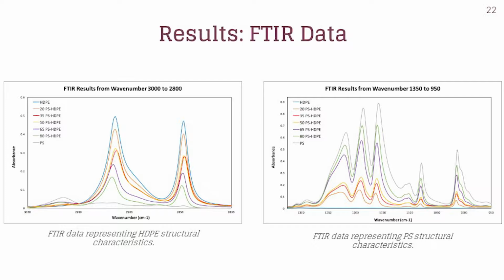Then if you look to the right, it's from wave number 1350 to 950, and these show the peaks that are associated with characteristics of PS. Here you see the opposite trend occurring: as the polystyrene percentage increases, the absorbance also increases. The FTIR tests confirm that the various percentages we think are in the compositions really are, as the trends are continual across our samples.